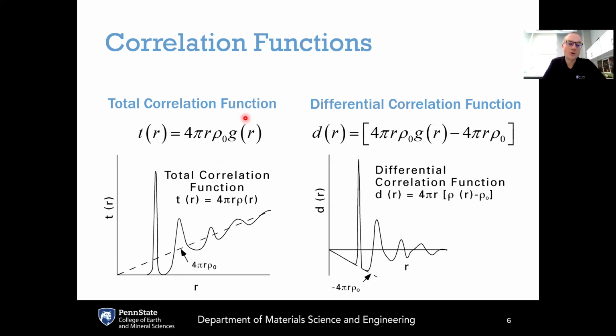One of them that can be defined is the total correlation function. The total correlation function oscillates around a line of 4 pi r rho 0 rather than the parabola of 4 pi r squared times rho 0. So this is the same thing as the radial distribution function, but just divided by r. So it's just 4 pi r. And in this case, this line here is 4 pi r rho 0, and the total correlation function is oscillating around that line. This is not used as much as the radial distribution function because the radial distribution function can be integrated to get the total number of neighbors, and that's not possible with this total correlation function. Sometimes the total correlation function is used just because it's more convenient to see some of the oscillations around a line compared to seeing the oscillations around a parabola.